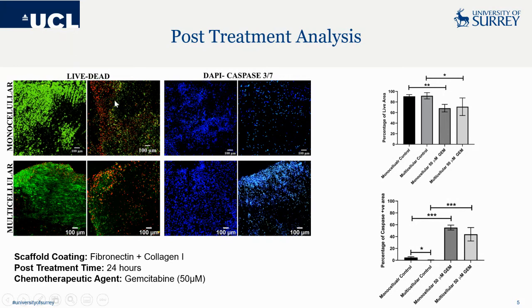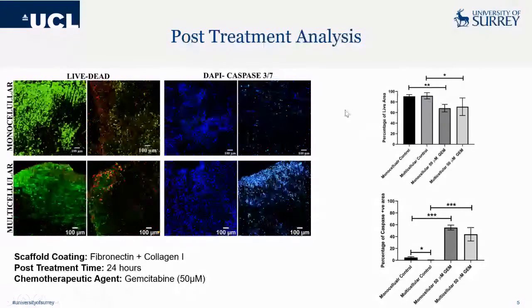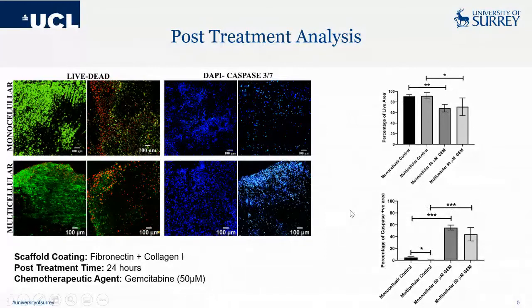What we saw is that you do have dead cells present in both the monocellular system and the multicellular system 24 hours post-treatment, suggesting that the chemotherapy was working, as well as quite a large number of apoptotic cells. On doing an image-based quantification of the live dead area and the caspase positive number of cells, we see a significant downregulation of live cells in both the monocellular and multicellular systems, and a higher number of apoptotic cells in both cases. However, we were unable to see any difference between the monocellular and the multicellular system as a whole.